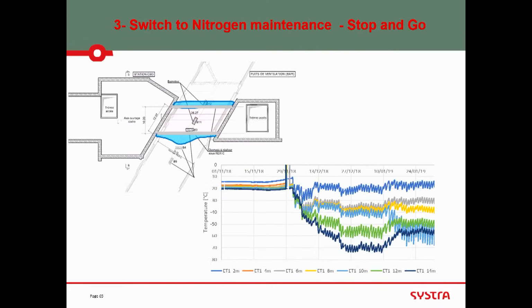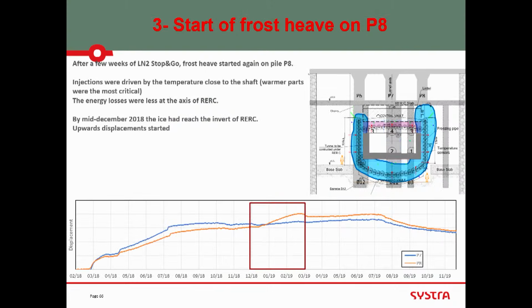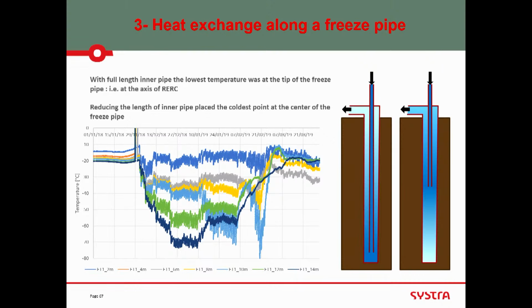In 2 words, we had to adapt because the thickness of the frozen area decreased drastically next to the boxes. So we were obliged to change the pipes. In the inner pipe, as you see, initially, it's always done like this. We have the outer pipe and the inner pipe, which gives the flow, the maximum cold at the top, at the bottom. We were obliged to cut the pipe by 2 so that the minimum temperature was at the middle of the pipe. And by changing, we were able to increase the thickness of the area which was next to the wall.